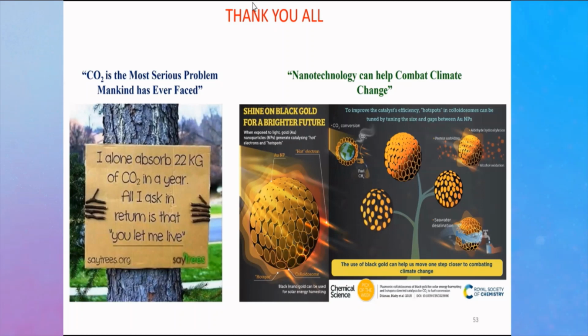Vanishka asked about the absorption spectra of the black gold, which shows a broad band. However, no plasmon peak exists there. So can such a system be used for catalytic processes, as only at the plasmonic excitation wavelength not all electrons can take part in the reaction? No, the broadband absorption is due to the plasmon. You must have seen only the plasmonic peak at, say, 550, but see why you have a 550 plasmonic excitation: because that gold cloud has a certain size and shape which will resonate at 550 nanometers.